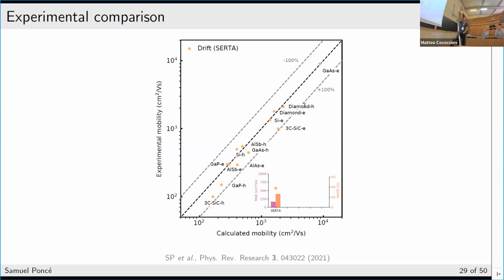And in fact, you can see that here you have some underestimation. So this is not very good. The reason is simply that we are using this self-energy relaxation time approximation. If we do better, and we do this iterative solution of the Boltzmann transport equation, then we start to overestimate as we would expect. But actually, what we are computing is the drift mobility.